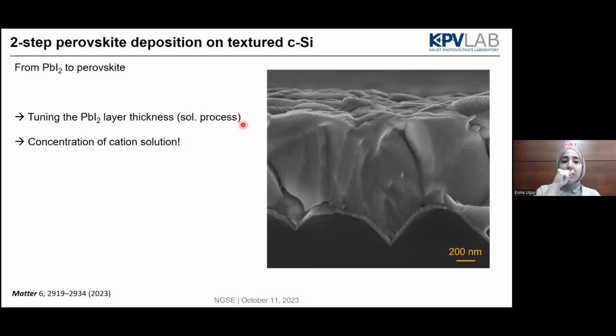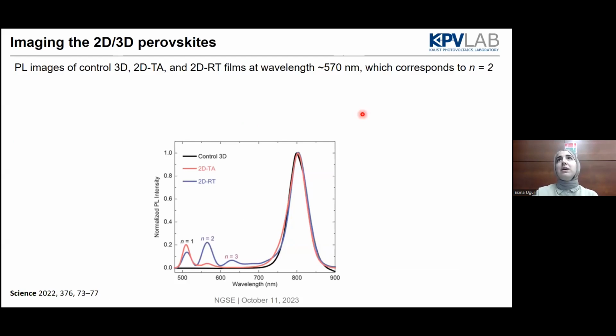But as I mentioned, especially when we put some charge transport layers, we might have some interfacial recombination. That's why we need to passivate the interfaces. Now here I use butylammonium-based cations, namely n-butylammonium or isobutylammonium, for the top of the perovskite. But when you think about the regular device structure, the light is coming from here, so we don't really think about the high exciton binding energy of the 2D perovskites, because for this larger cation we are expecting to have the lower dimensional perovskites. In this case, now we have a challenge: the light is coming from the top, and first it will see the 2D perovskite, which has the high exciton binding energy.